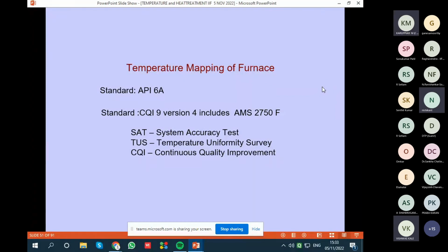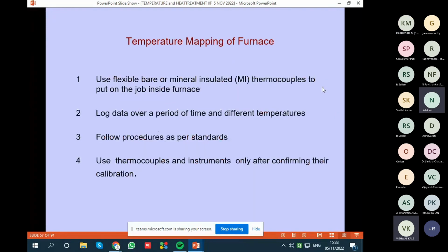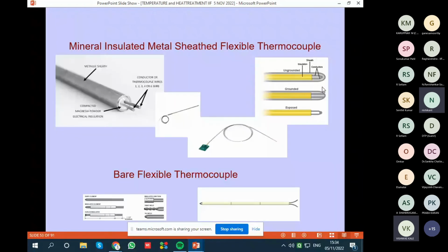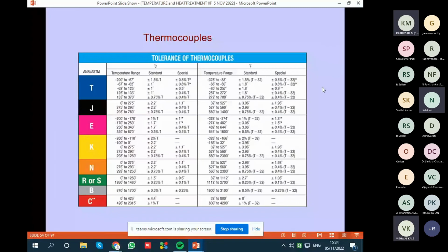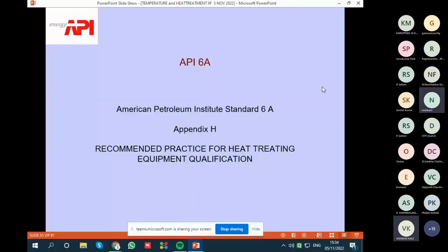What is API 6A? We just put bare thermocouples inside the furnace near the job. We measure the temperatures, follow the procedures, and we use the thermocouples only after confirming their calibration. These are the thermocouples I talked about some time back. Very flexible thermocouples we put inside the furnace. We use the proper thermocouple depending on our range. And this is the standard. So this is my furnace, and I put 9 thermocouples at 9 locations.